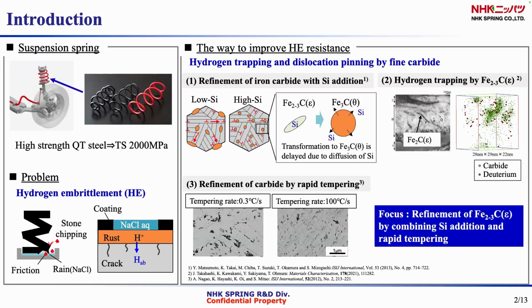We focus on the epsilon carbide in this study. It is known that when silicon is added in steels, the carbides are finely precipitated within grains. Silicon is said to delay the transformation from epsilon carbide to cementite type.